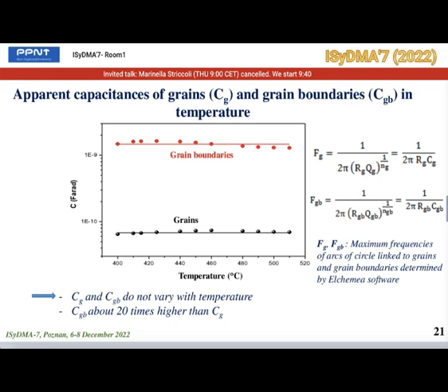The apparent grain boundaries capacitance is 20 times higher than that of the grains, and both do not seem to vary with temperature.